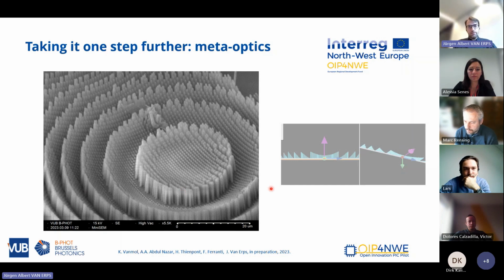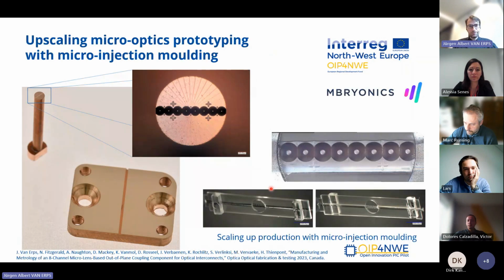More recently, we've been looking at meta optics, so meta surfaces where you basically represent the lens functionality by making very small arrays of high aspect ratio pillars, which are typically made with electron beam lithography, but then you are limited to one height across the structure. And again, we exploit the advantage of the full 3D freedom of 3D nano printing to enable arrays of nanopillars, which have also got varying heights. So we can again optimize the optical functionality.